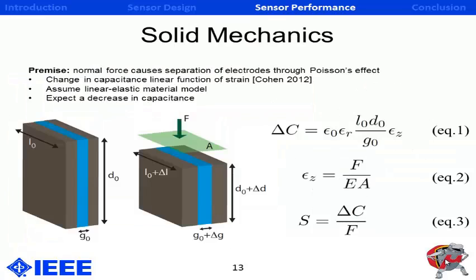An analytical solid mechanics model was developed, and the premise is, again, pretty simple in nature. A normal force causes the material to flatten and separate. That causes a separation of the electrodes through Poisson's effect. The change in capacitance has been shown to be a linear function of normal strain, epsilon z, thanks to work done by Cohen in 2012, as shown in equation 1. In equation 1, we have the vacuum permittivity and the dielectric constant and the normal strain that I just mentioned. And L, D, and G naught are all the initial geometric parameters of the electrode.